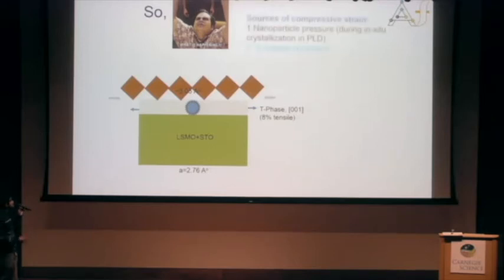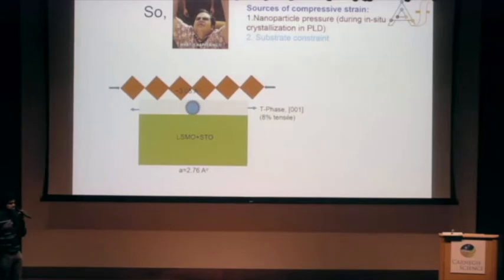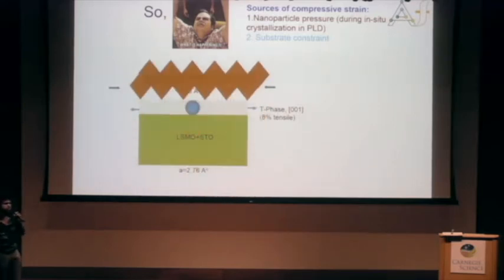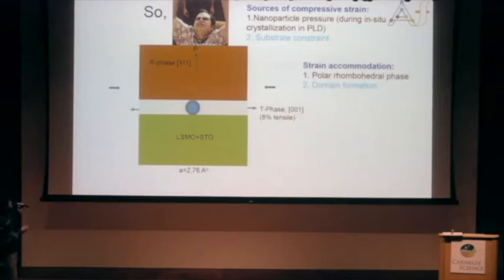And in fact, this is well known in the literature of zirconia. What happens in PLD, for instance, is there is in situ crystallization, so we have the formation of nanoparticles. That is one source of compressive stress. And then the second one is the substrate constraint. So using these two, we actually compress this cubic or tetragonal phase into a rhombohedral phase. What we have is a well-oriented R phase with a polarization which is out of plane. So the strain is accommodated by polar rhombohedral phase and domain formation, which is a standard trick to accommodate strain.